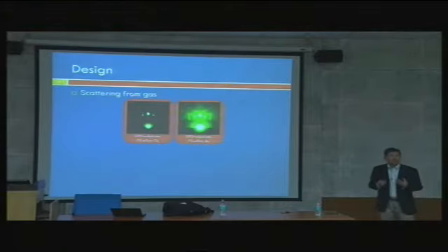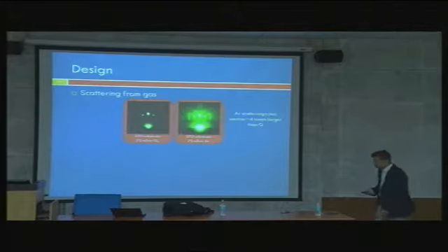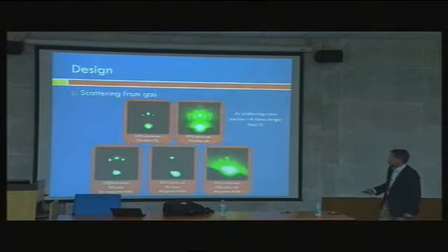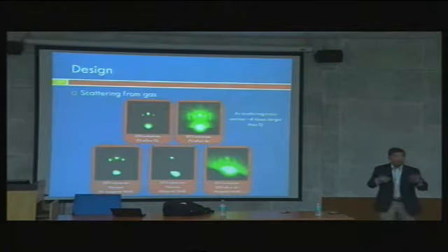So it's a more stringent requirement to grow this material system. The argon scattering cross section is 4 times larger than oxygen, and at 200 millitorr, a high pressure, you get a lot of diffuse scattering.